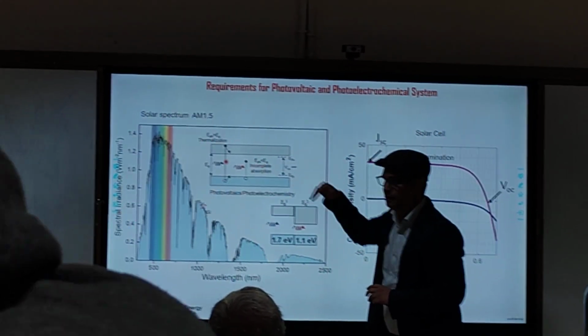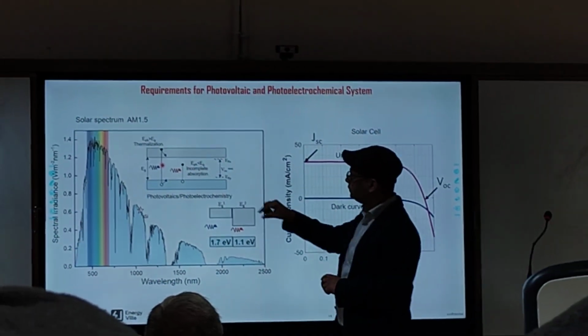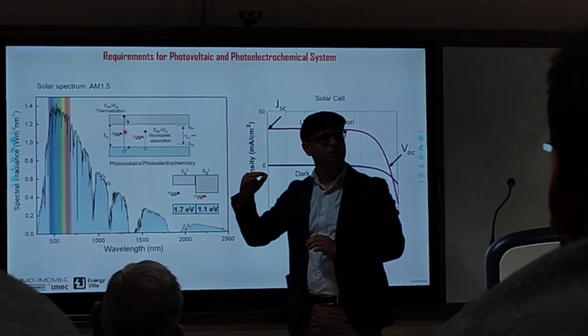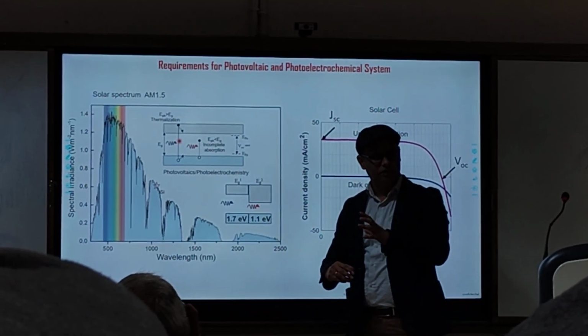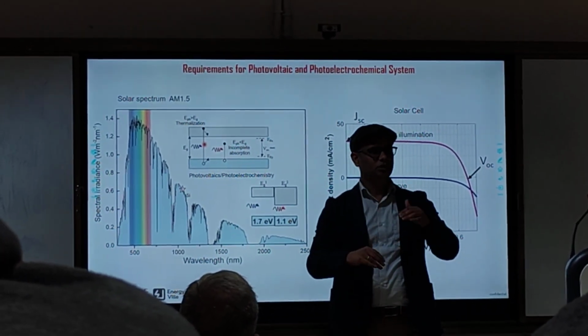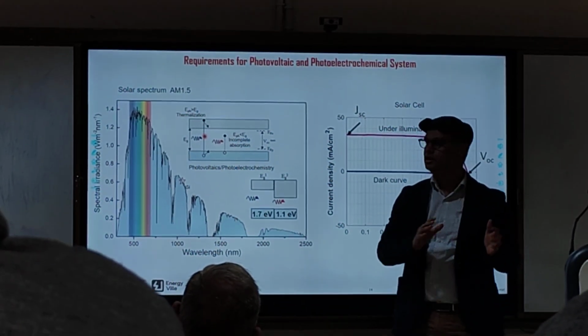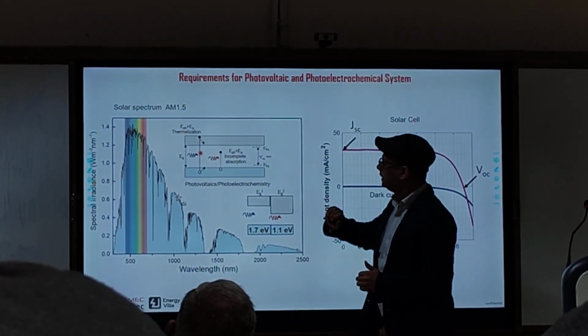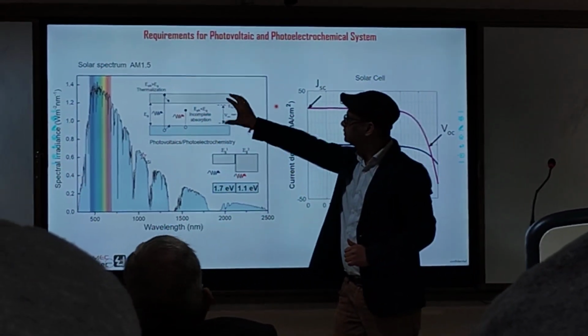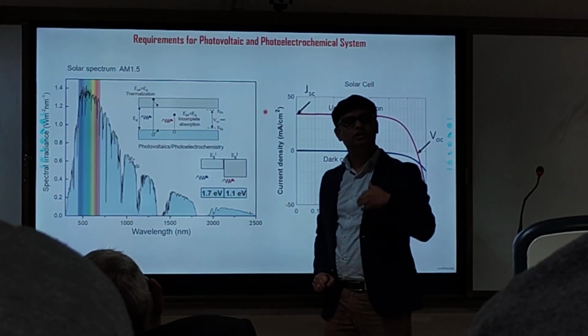The maximum voltage that you can get is not the difference between the conduction and valence band. It's not true, because you have something called the quasi-Fermi level. Imagine a p-type semiconductor where the Fermi level is close to the valence band. As soon as you shine light, you generate minority carriers, which are electrons. Now the distribution of electrons and holes cannot be given by one Fermi level because the picture is out of equilibrium. So you need to have these quasi-Fermi levels. The difference of these two actually gives the maximum voltage, not the conduction and valence band. This is a quantity called quasi-Fermi level splitting. You can actually determine it.